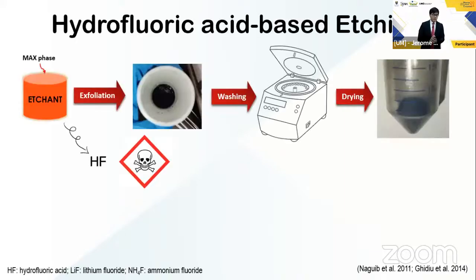There are a couple of approaches to making it, but they generally revolve around removing the A layer out of the MAX phase. The first ever discovered MXene was titanium carbide by two researchers in Drexel University in 2011. In the hope of fabricating better electrodes for lithium-ion batteries, they immersed titanium aluminum carbide MAX phase in pure hydrofluoric acid. This hydrofluoric acid etches and exfoliates the MAX phase, producing a black viscous substance that was subsequently dried and washed, forming the MXene we know today.